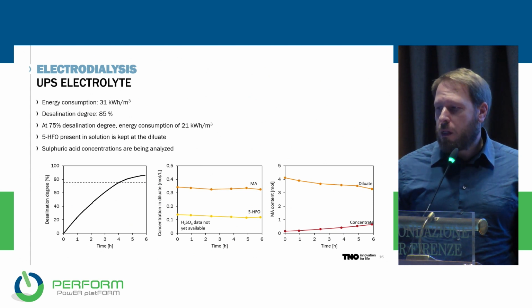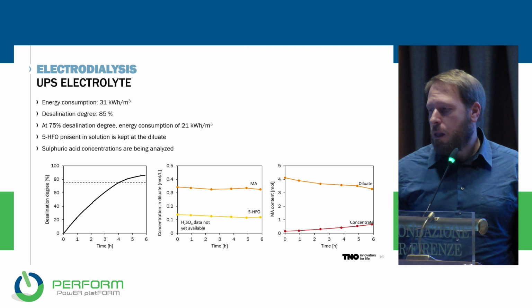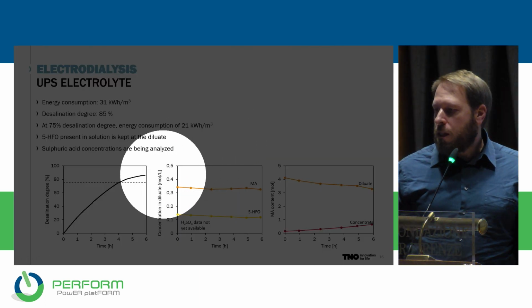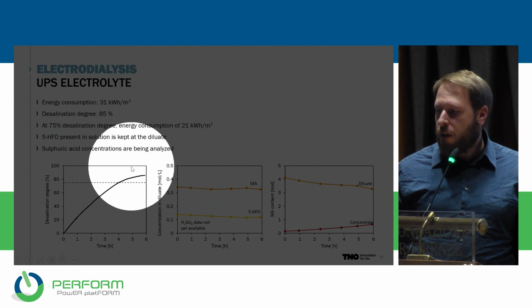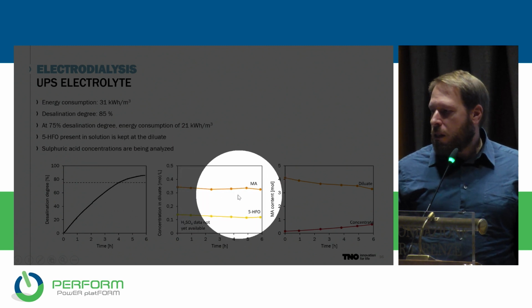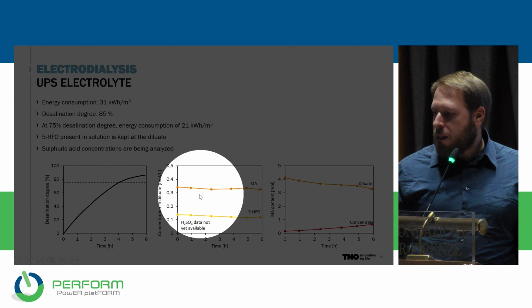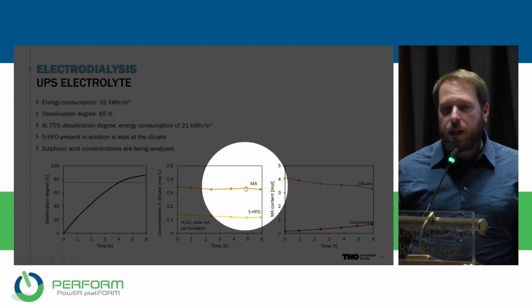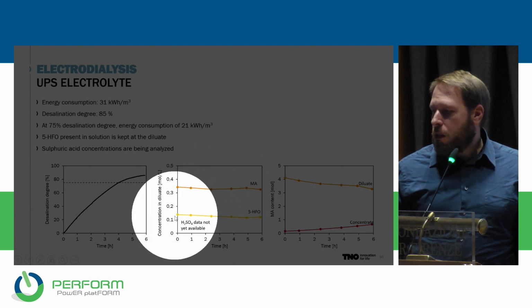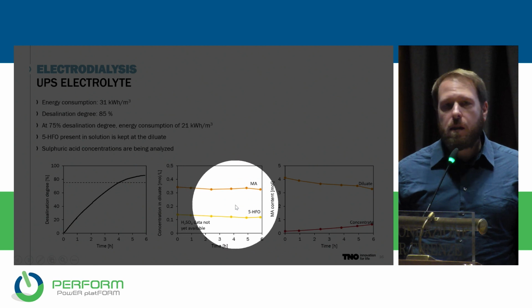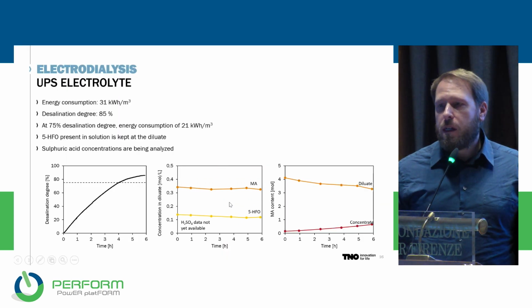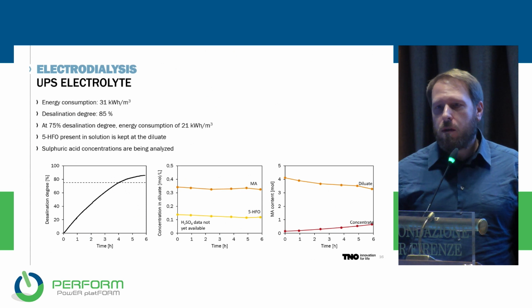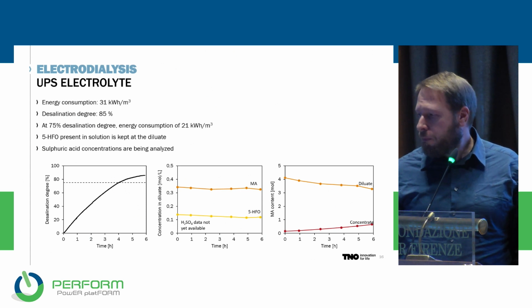Next, we actually look at the real sample. So this is data from the real electrolyte that we got from the upstream unit, and again, in this case, we push desalination a bit further to about 85%. But you can see that the maleic acid that we get is very constant. And also here you see that 5HFO stays in the same solution, but after crystallization of maleic acid, we can recycle 5HFO back to the upstream.